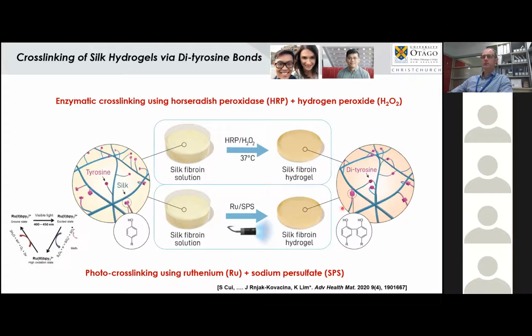And in this particular case, we're trying to work out, could we utilize this to allow cross-linking of silk fibroin? Again, another alternative type of hydrogel, which provides a range of cell instructive capability that's completely different from gelatin-based systems. So we're trying to look at oxidizing these different aromatic residues such as tyrosine within this process. And because we have a number of these tyrosine-rich proteins in silk, we were trying to work out whether we could look at cross-linking using dityrosine formation within these native tyrosines that were present within silk.